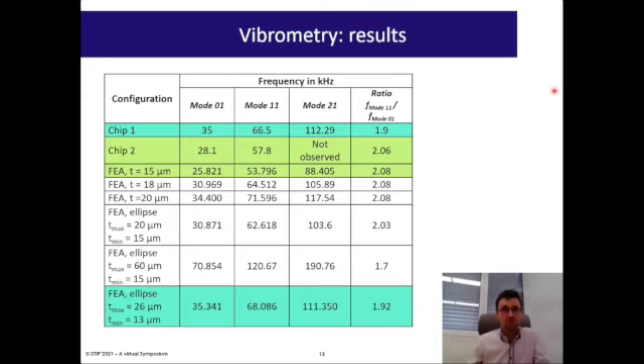We can also see that one of the membranes behaves more like a membrane with uniform thickness, while the other one behaves more like a membrane with an elliptic shape. Let's look at the frequencies. Using the equation of the frequency presented before, we were able to estimate the stress within the membranes, and we evaluated it at 15 to 50 megapascal.